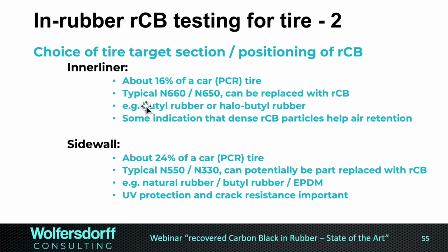The sidewall sometimes is a mixture of N500 and 300 grades, and it can potentially be partly replaced. Here, really, we have the natural rubber, butyl rubber, sometimes even EPDM. It's a very complex system because we have mechanical crack resistance, which is important, but also the UV protection. And for UV protection, the carbon blacks typically are higher structured, higher surface area carbon blacks.